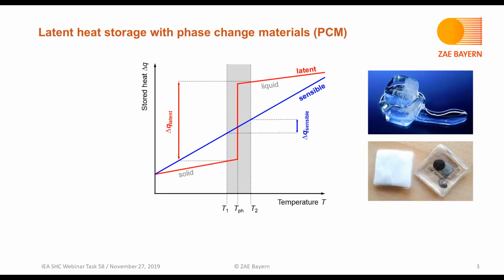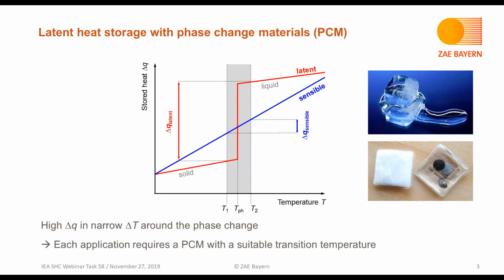Examples of this technology, as Wim already introduced, is ice, the transition from ice to water at 0 degrees C, or what is also very well known are these heat packs. They are using a salt hydrate with a melting temperature around 58 degrees C. So as you see on the figure, PCM, phase change materials, provide a high amount of stored heat in a narrow temperature range around their phase change. And that means that each application requires a material with a suitable transition temperature, let's say suitable melting temperature.